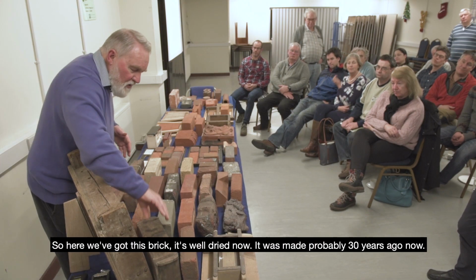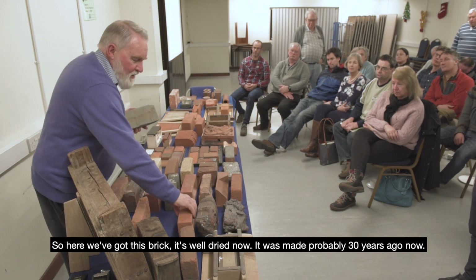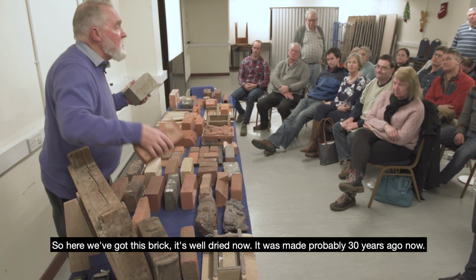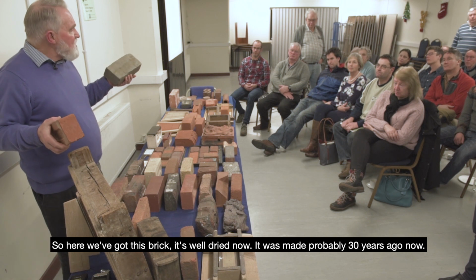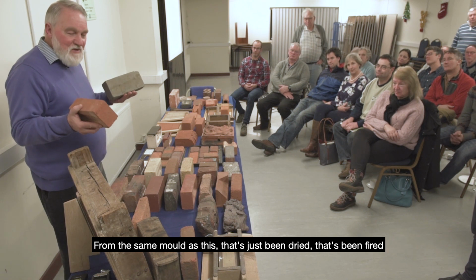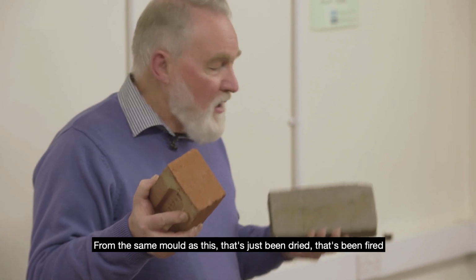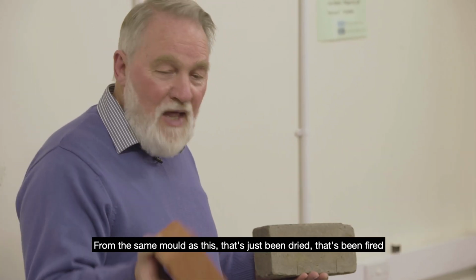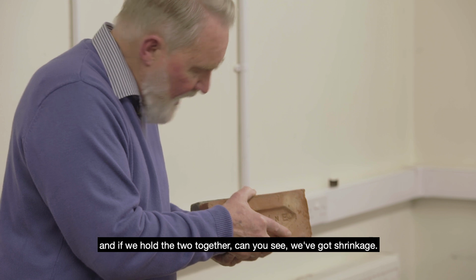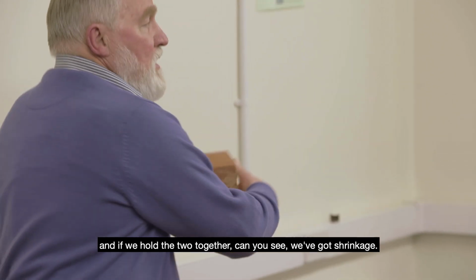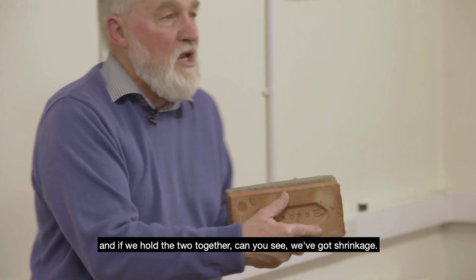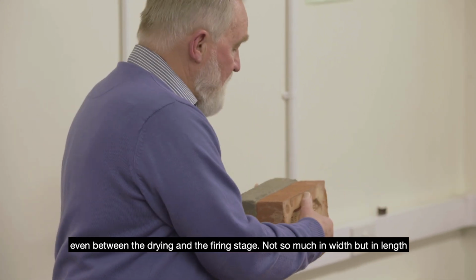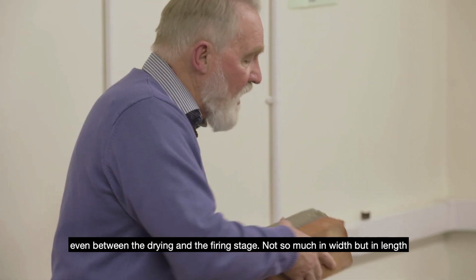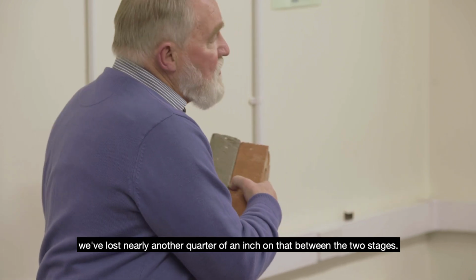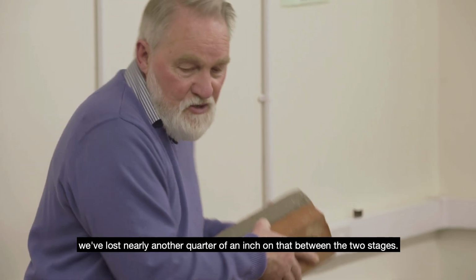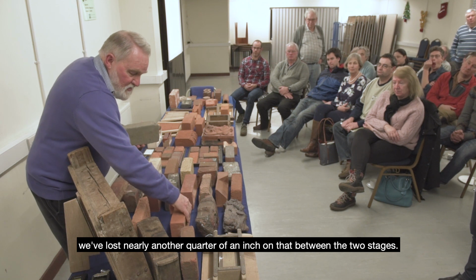So here we've got this brick, which is well dried now. It was made probably about 30 years ago, from the same mould as this. That's just been dried, that's been fired, and if we hold the two together, can you see that we've got shrinkage even between the drying and the firing stage? Not so much in width, but in length, we've lost another nearly a quarter of an inch between the two stages.